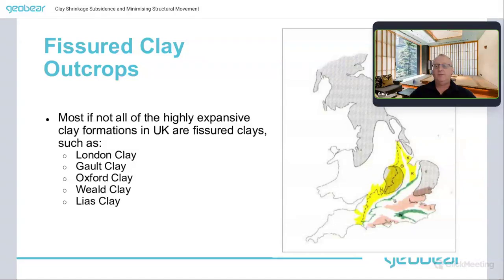For the purposes of this conversation, I'm going to focus on fissured clays, because the vast majority of claims, not all, but a significant percentage of claims due to subsidence damage are on these particular formations. And of those formations, London clay is the single most commonly occurring strata underneath buildings which are suffering from clay subsidence. And that's a combination of the fact that it has a high plasticity index, and it's also where there's a lot of houses. So the correlation between where the houses are and where the clay is centres on London. But these formations do crop up generally in the southeast of England.